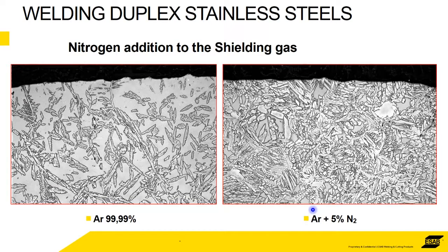So these two photographs illustrate, on the left hand side, a weld made with no nitrogen. You can see in the fusion line we've got very big areas of ferrite. Okay, these dark areas are ferrite, basically pure ferrite. So this means that you don't have a duplex structure, so in these areas you don't have the corrosion resistance and you don't have the mechanical strength. If you compare that to, say, 5% nitrogen, typically we'd recommend 3, but this was in a laboratory. The addition of nitrogen has basically converted the ferrite to austenite. You've got a lovely duplex mixture all the way to the surface.